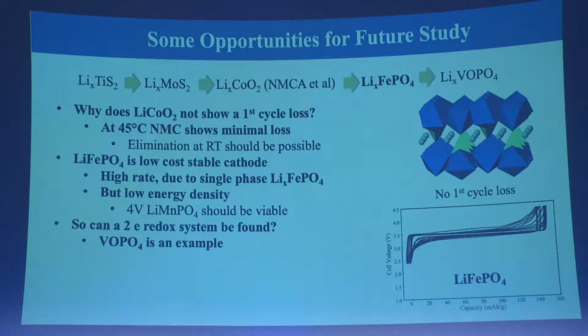And they got taken over by a Taiwanese company, and they switched to graphitic anodes in there. But the interest then moved away from the layered oxides. I say interest, the research interest. Us folks wanted to do something different, to look at the phosphates, and I show you the structure here of lithium iron phosphate, a tunnel structure, so much more stable. But I said it carries phosphate groups with it, means it stores less energy.